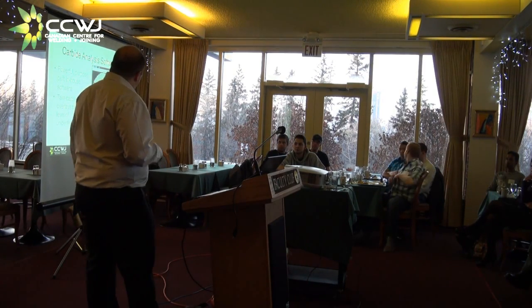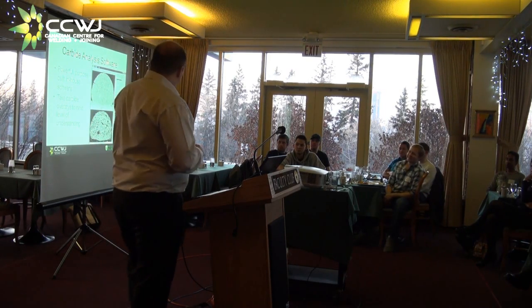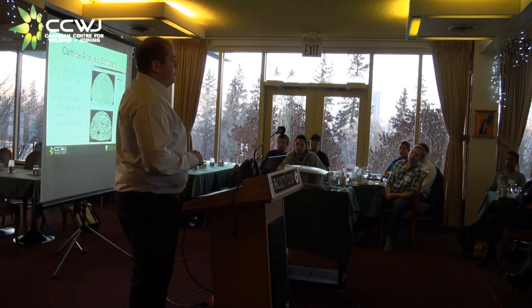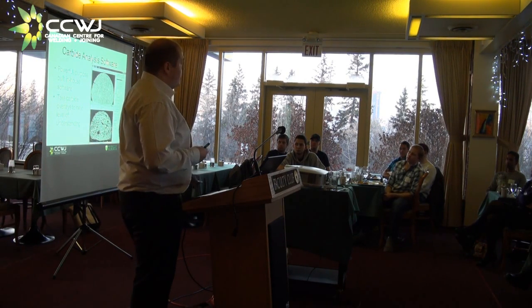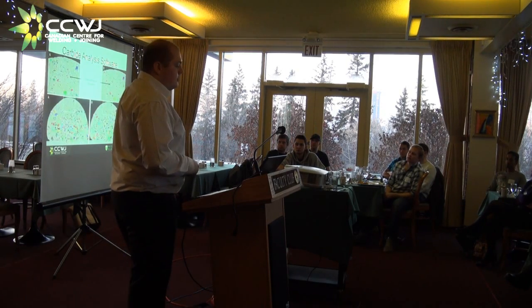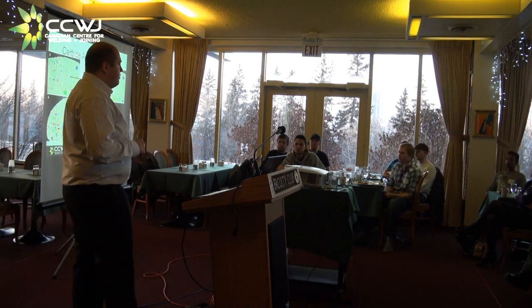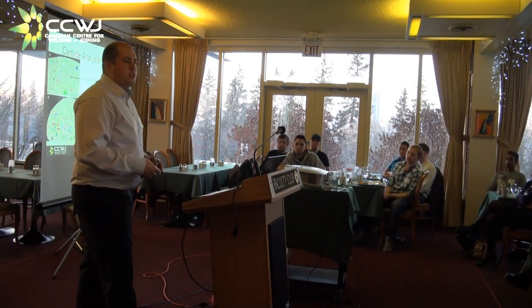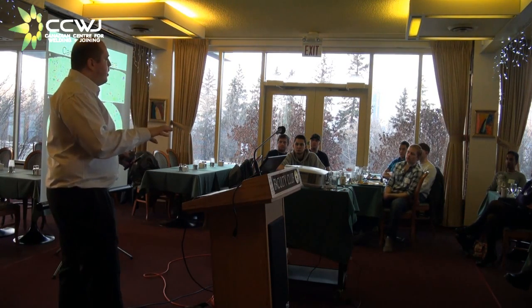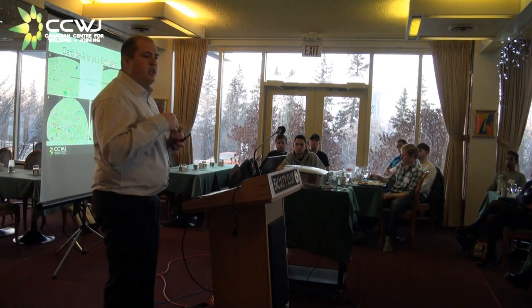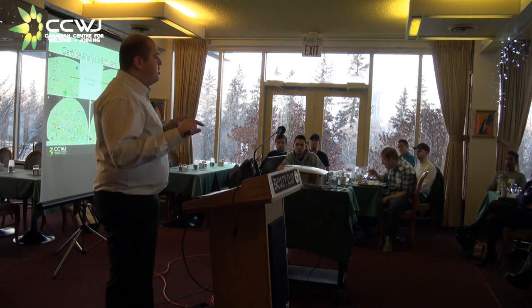Basically, we can take an overall image, a very high magnification, high resolution image. Typically, some of these pictures are thousands and thousands of pixels big, so we have really good data to work from, and we can do image analysis on it. Now, measuring the tungsten carbide fraction in an overall weld bead is nothing new. What we're doing is now being able to separate out the primary tungsten carbides that survived welding and give us our good properties, from the detrimental secondary ones, which reprecipitate if we overheated our weld pool. And now we can differentiate between the two.